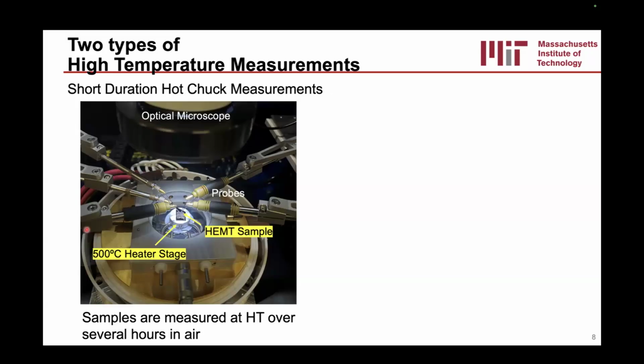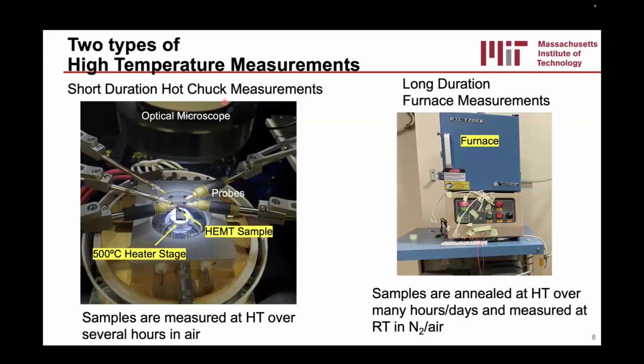Usually this is in air, and usually takes about several hours, maybe 5 to 6 hours in total, 1 hour at each temperature or so. The other type of measurement are what I'll call long duration furnace measurements. Here we're putting our devices in an oven, annealing them basically at 500 C for several hours or for several days, and then measuring those devices at room temperature to understand the degradation and how the devices change over time. So I'll try to emphasize each time, but just so you're aware.